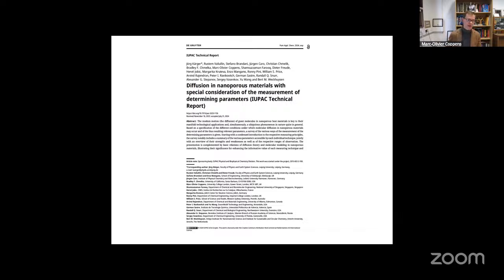So you can directly measure diffusivities for various conditions, say various temperatures, various pressures, so that gradually you change the mean free path. And you would see then this transition going from the pure molecular to the Knudsen diffusion regime. However, in mesoporous materials with a few nanometers in size, even at ordinary pressures, you will find that the mean free path is typically larger than the local pore diameter. And so this Knudsen diffusion becomes even the dominating one. Yeah, okay, makes sense. Thank you.